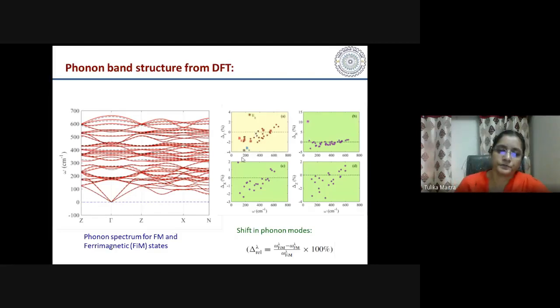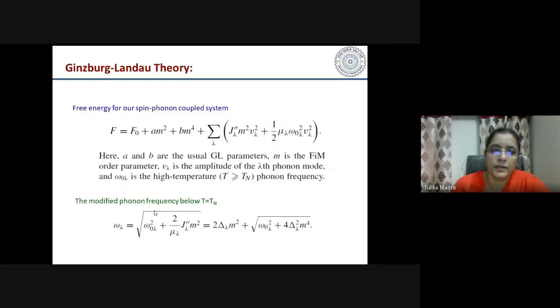So this shift, because it is connected to this spin phonon coupling, we can directly use it and do a Ginzburg-Landau-like theory. This is the free energy for Ginzburg-Landau theory, where M is the ferrimagnetic order parameter, A and B are the usual Ginzburg-Landau parameters, and V lambda is the amplitude of lambda phonon mode, and this is the term which was there without any magnetic order.